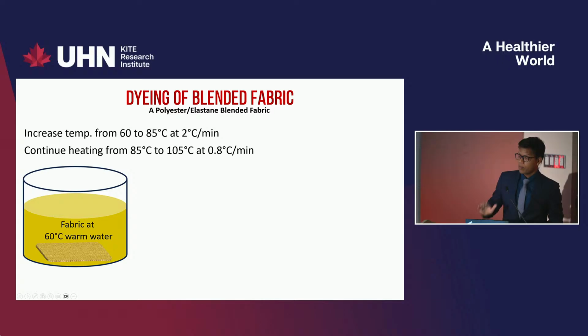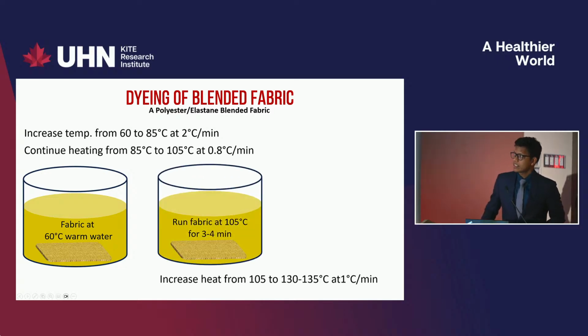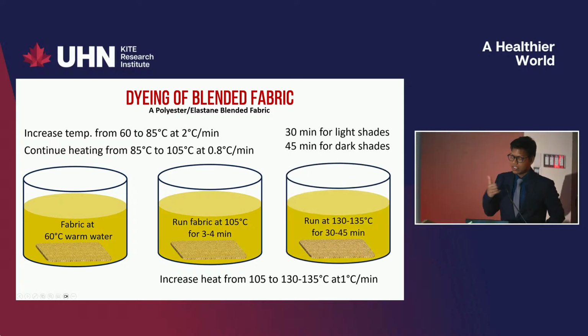And then from 85, we're going to reach above the glass transition temperature, we'll reach at 105. So at 105 degrees centigrade, the polyester is almost softened, and we try to give a short hold on that temperature. And now this is the process of the dyeing. So we reach above the glass transition temperature, where fiber makes the space to take the dye inside them. So for this fiber, we go for 130, 135 degrees centigrade temperature, and we run for 30 to 45 minutes.